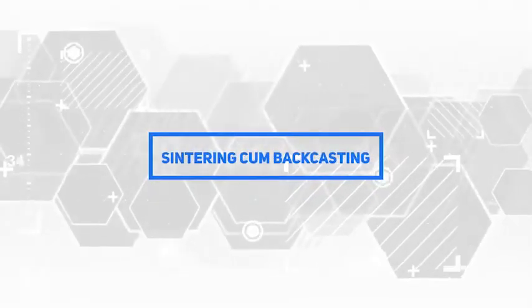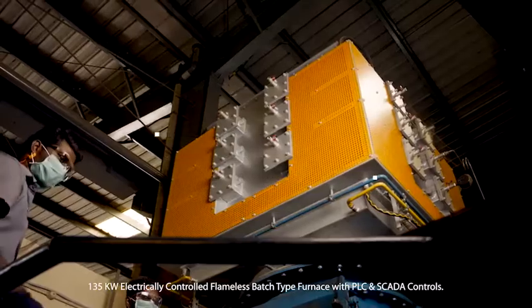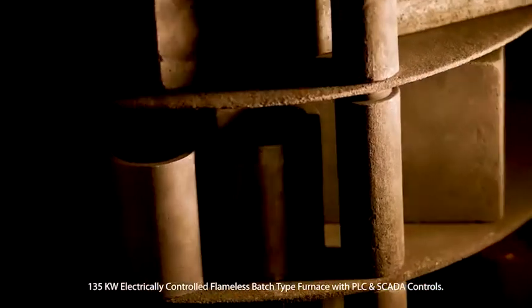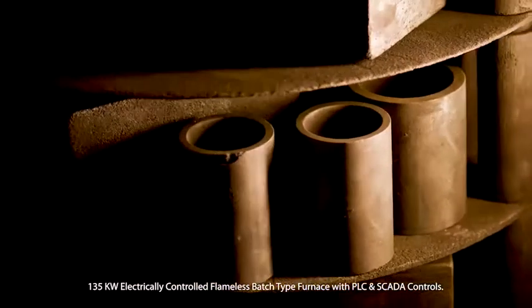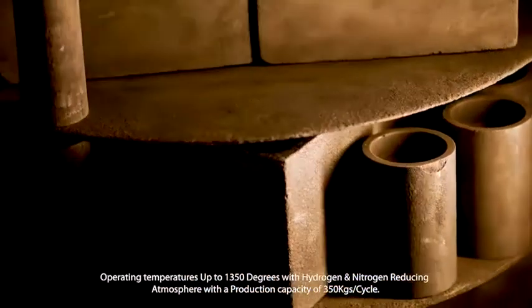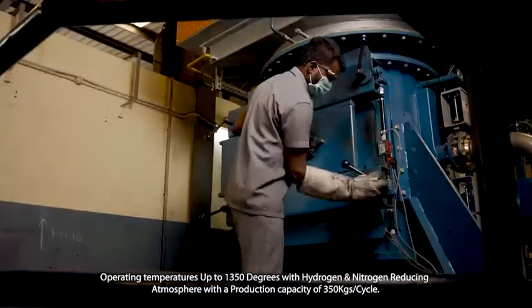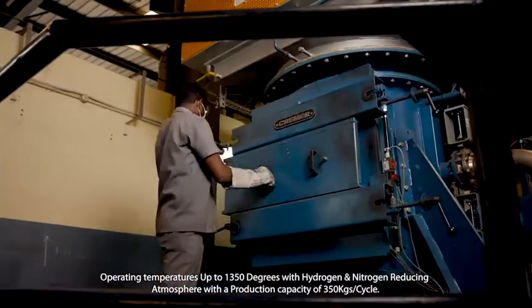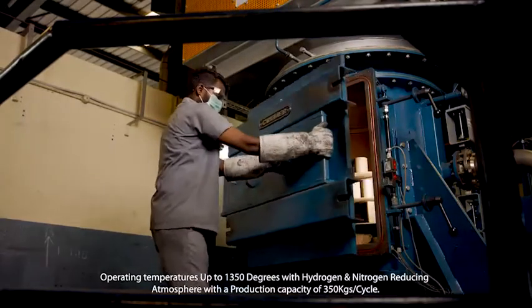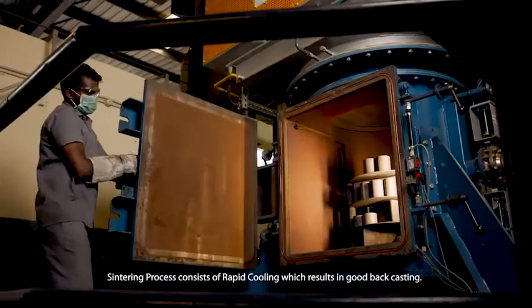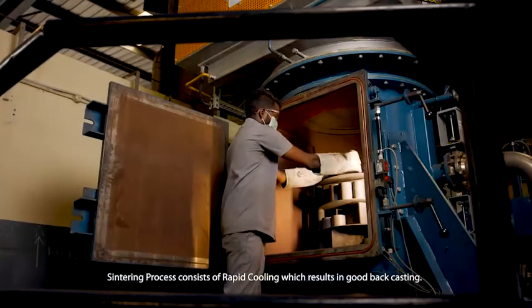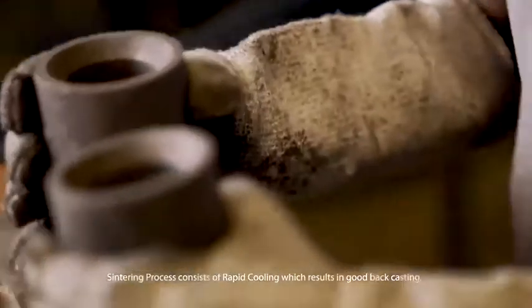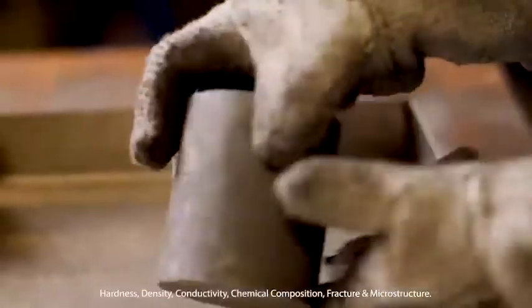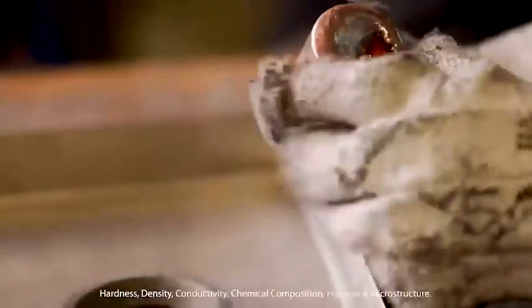Sintering cum back casting. 135 kilowatt electrically controlled flameless batch type furnace with PLC and SCADA controls. Operating temperatures up to 1350 degrees with hydrogen and nitrogen reducing atmosphere with a production capacity of 350 kg per cycle. Sintering process consists of rapid cooling, which results in good back casting. Sintered components are subjected to various tests such as hardness, density, conductivity, chemical composition, fracture and microstructure.